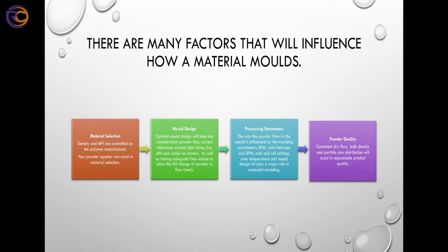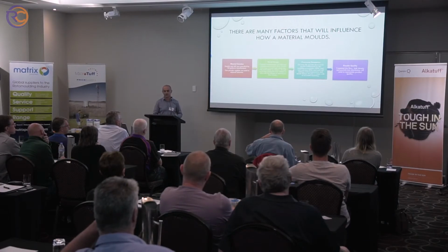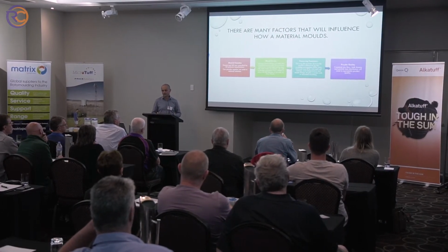Optimal mould design will take into consideration the powder flow, correct tolerances around tight areas, kiss-offs, radiuses in the corners, as well as having adequate free volume to allow the powder to flow around the mould. Processing parameters. The way the powder flows in the mould influences the moulding parameters. So the RPM, rock and roll machines, oven temperature, all play an important role. And then finally the powder. A consistent dry flow, bulk density and particle size distribution will help you make a repeatable product.